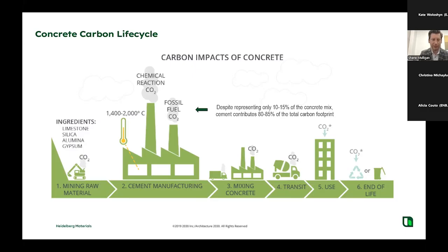And that relates to the process of making cement itself. There are two main contributors to increasing the carbon intensity of the cement manufacturing process. One of those is known as combustion emissions, which is related to the burning of fossil fuels to heat the cement kilns to the 1500 degrees Celsius that's necessary to make cement. That's generally achieved using materials like natural gas or coal, or in some cases petcoke, which burns a lot of CO2 into the atmosphere as a result of those high temperatures, and ultimately represents somewhere in the range of about 30% of the total cement intensity for emissions.